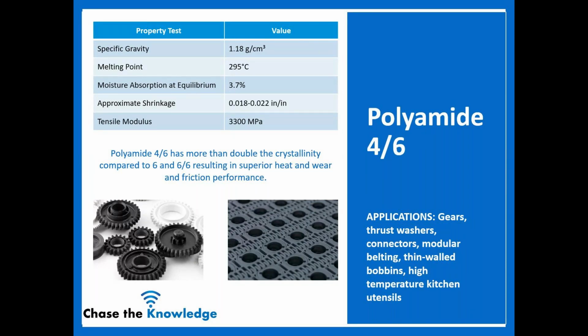6.6 is 250, so we get, again, a 45-degree swing on melt temperature, so higher heat, and then better wear and friction performance. We already know that nylons are used in applications for wear and friction, but something like a PA 4.6 has superior performance, specifically in places where you have higher pressures and higher velocities. So if you're pushing it hard or trying to get it to move really fast, a 4.6 could be an excellent option. With the downside, as hopefully we're starting to connect the dots, that shorter chain picks up more moisture. So as you can see, 3.7% picks up a lot of moisture, but it's high heat, great for wear and friction applications.